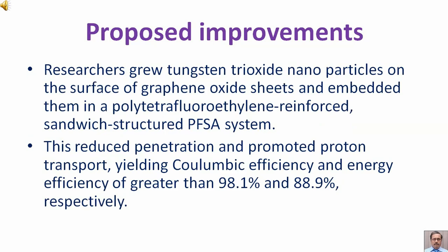Researchers grew tungsten trioxide nanoparticles on the surface of graphene oxide sheets and embedded them in a polytetrafluoroethylene reinforced sandwich structured PFSA system. This reduced penetration and promoted proton transport, yielding coulombic efficiency and energy efficiency of greater than 98.1% and 88.9% respectively.